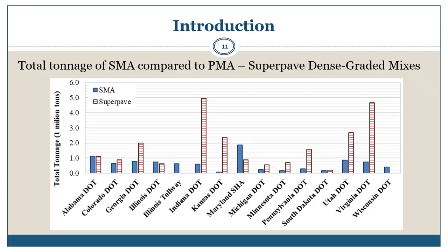This slide shows a bar chart graphical comparison of the total tonnage of SMA mixtures versus Superpave dense graded mixes that have been reported by some agencies. SMA mixtures are only used for the wearing surface, while the Superpave polymer modified dense graded mixtures can be used for other asphalt layers, so the tonnage is greater for the dense graded mixes in comparison to the SMA mixtures. SMA mixtures are not typically used as a base mixture or as an intermediate asphalt layer. They're primarily used for the wearing surfaces.